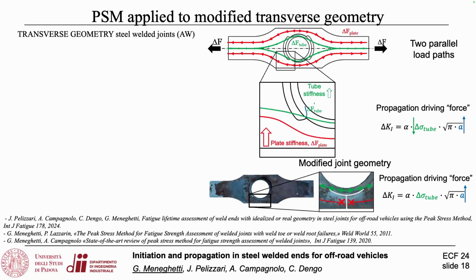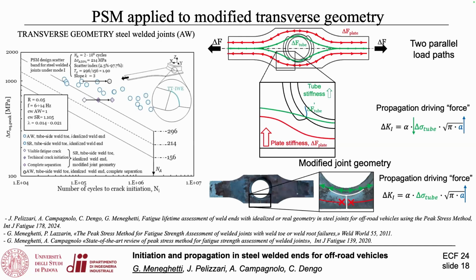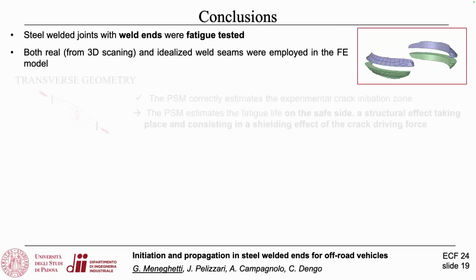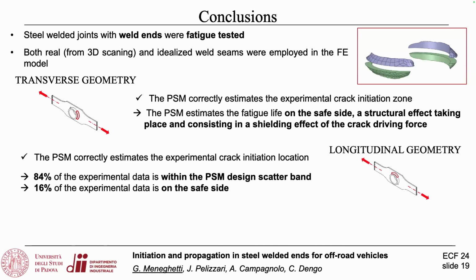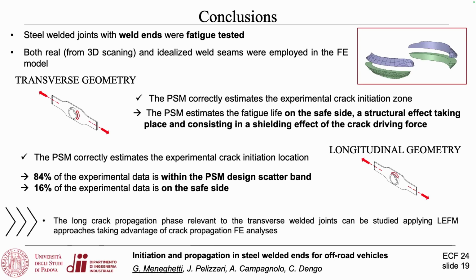So to test if this physical interpretation was correct, we simply cut the net section and we tested a new joint. If this reasoning is true, now we tested simply a welded joint where the stress flow has to engage the welds because we do not have a structural path through the plate. And doing that, you see that the joint came into the design scatter band. So in conclusion, we successfully tested the transverse and the longitudinal geometries, and in the end, we predicted the crack initiation point and the fatigue life with that correction I have shown.